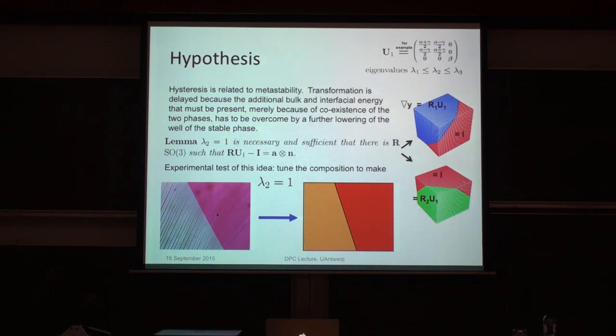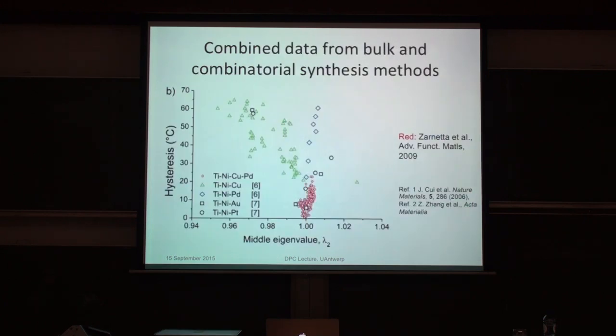So we did it, and other people did it, and combinatorial synthesis experts did it, and the results are truly remarkable. And here's one of the graphs. This is in a whole family of alloys with nickel and titanium and various third elements. And each dot has a different composition. And this is a measurement of the width of that hysteresis loop that I showed earlier. And of course, each one has a different composition. I could plot that versus composition, but now I've replotted it versus the middle eigenvalue. And you can see there's a very, very dramatic drop. In fact, a very sharp drop of hysteresis versus this middle eigenvalue.